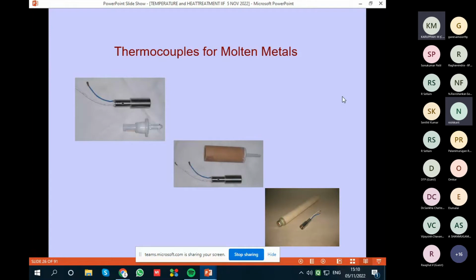The thermocouple in the middle is a multi-dip thermocouple with a ceramic tube and with a long tube which has come out about 80 mm long. It contains platinum rhodium wire and there is a connector there. This multi-dip can be used at least 5 to 7 times in a molten bath. But you have to dip only the quartz tube end in the molten metal. If you take that care, and when you take the multi-dip out of the molten bath, you just have to make sure that the metal does not stick to the quartz tube. Then you can use it again and again. That is why we call it a multi-dip.